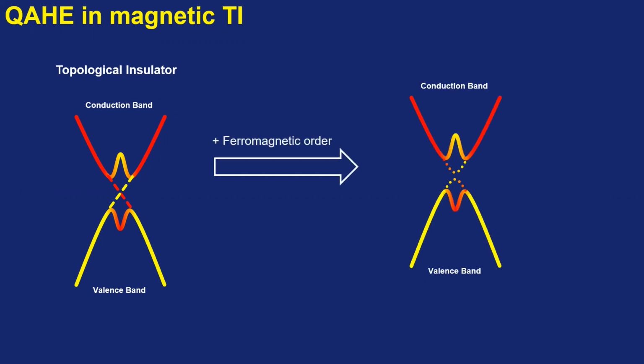If we introduce ferromagnetic order in the topological insulator, the time reversal symmetry is broken, and a gap will open at the Dirac point. This is the bulk gap, and this is a gap within the bulk gap. This gap is usually very small. Theories predicted that if we can tune the chemical potential exactly into this magnetic exchange gap, in principle we will realize the quantum anomalous Hall effect. This is just a theoretical picture of how to realize the quantum anomalous Hall effect in a magnetic topological insulator. Let's move to the experimental side.